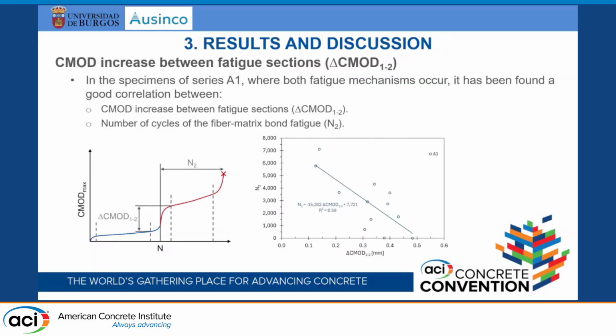And finally, there is another parameter that can have a certain relationship with fatigue life, which is the CMOD increase between sections, between the two mechanisms. In A1, in which we have this full general curve, we have found that there is a good correlation between the CMOD jump between the two mechanisms and the fatigue life, so that as this jump increases, the fatigue life becomes lower, with also a good correlation, but not as good as the one with the CMOD rate.